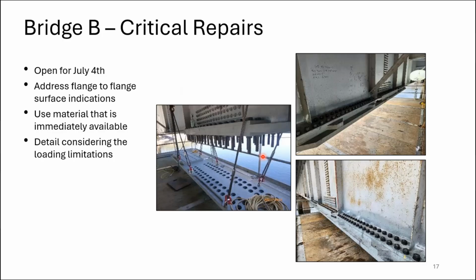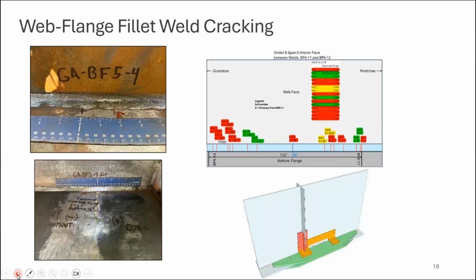We were also limited with how wide we could go by what bolts we could get, not only their grade, but also the length of bolt we could reasonably procure during this time frame. And all of this had to be detailed in close coordination and collaboration with the contractor in order to consider those load limitations on the bridge. Again, as I said, at this point is when we started finding a lot of this web flange fillet weld cracking. And Francisco will talk more about the solution, but that really changed the direction of where our permanent repairs were going. The substructures were load limited. There were some load reasons that we couldn't add additional load to the substructure units as well. So we were trying initially to keep these local to minimize any increase in loading on the structure.